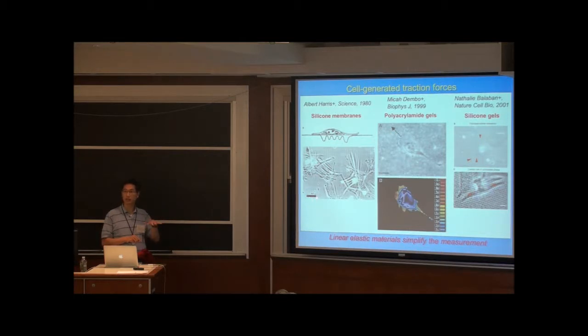They put cells on, they could tell when there were forces. And at some point, people started wanting to know not just a digital answer, is there force or is there not force, but is there more force and how much more force? And so it turns out that this problem of looking at this buckling, if you will, is fairly complicated, right? You can generate a wide range of forces that would change the degree of buckling. And so now you're trying to do the inverse problem where you see buckling and you're trying to back out how much force there is. And that turns out to be a highly nonlinear process, so it's very hard to quantify.